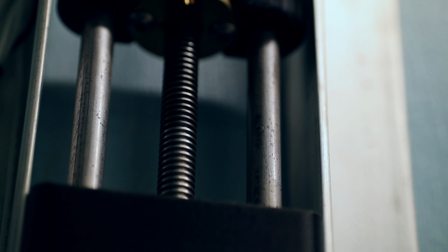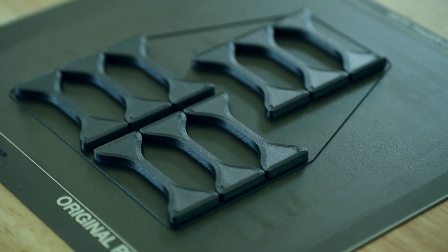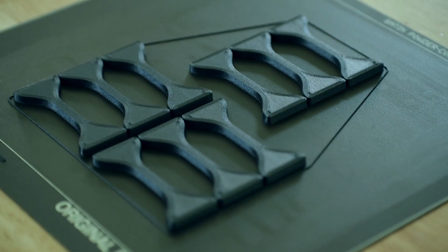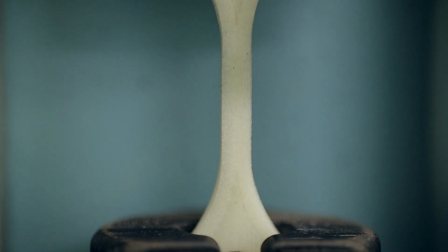The testing I did was all tensile testing. I printed the samples on my Prusa MK3 3D printer horizontally on the bed, and I used enough walls to make sure that all of the lines were aligned in one direction so that layer adhesion or interline adhesion was not a factor. So what we're testing in this video is the absolute material strength of the filament and not just layer adhesion.